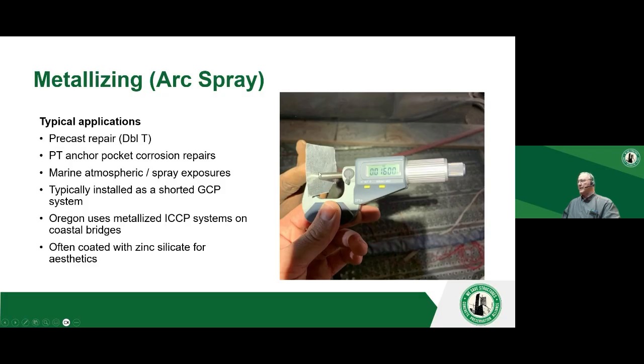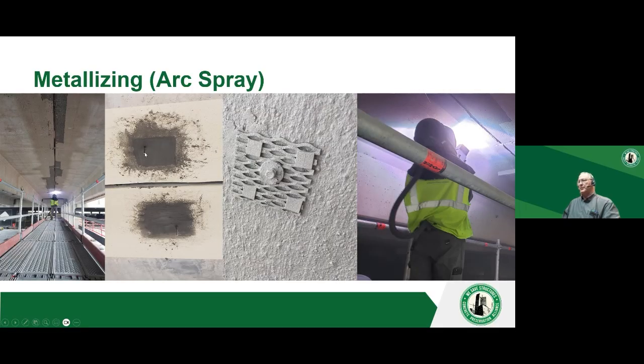You make sure you have thickness on here. This is 16 mils. Typically it's a 12 to 15 mil specification. And if you do it at the anchor pockets for PT, that's very common. In precast for the double T's, a lot of times it's a shorted system, and you can use metallized impressed current systems as well. This is a structure connection. Basically what you're doing is you're putting a bolt into the reinforcing steel, you patch it back, you put this zinc expanded mesh over top of it, and then you metallize it. It's very simple, very quick, and it's a very durable system.